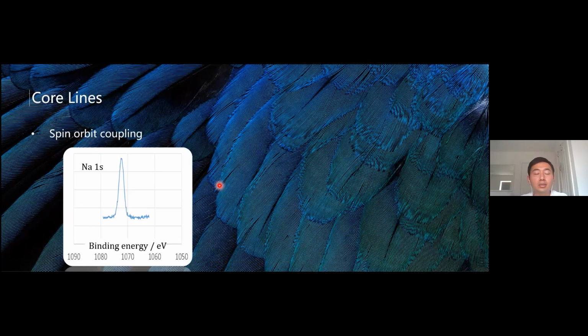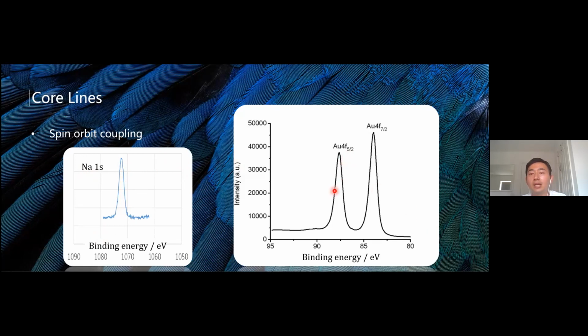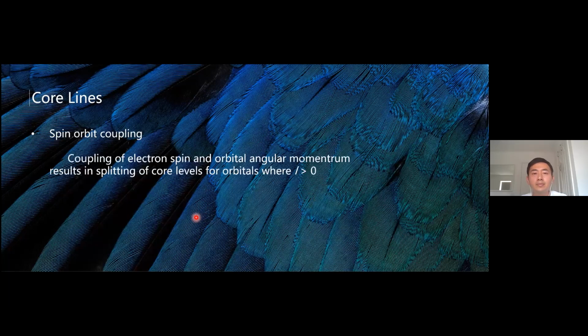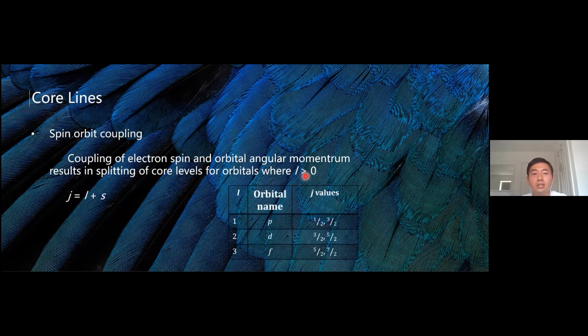Not all the peaks are as simple as sodium 1s peak, which is just one peak. There could be spin orbit coupling. For example, this gold 4f has doublets, and the doublets have a certain relationship between them. So the coupling happens when the electron spin and the orbital angular momentum, and when the orbits are, when the L is greater than 0.